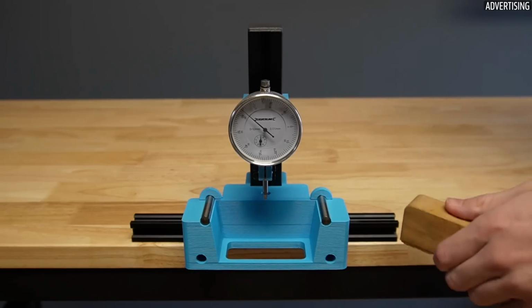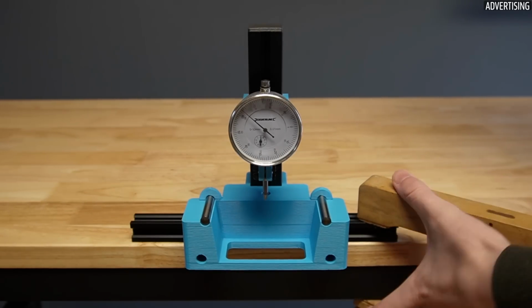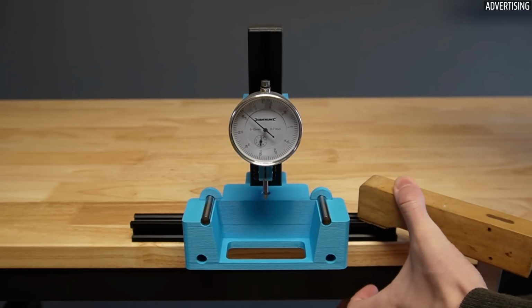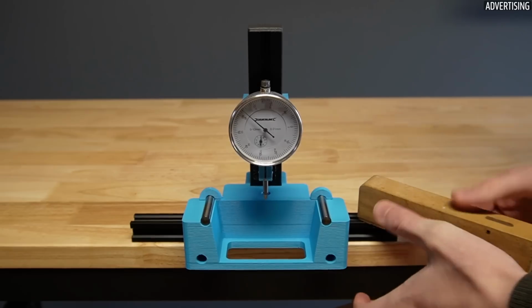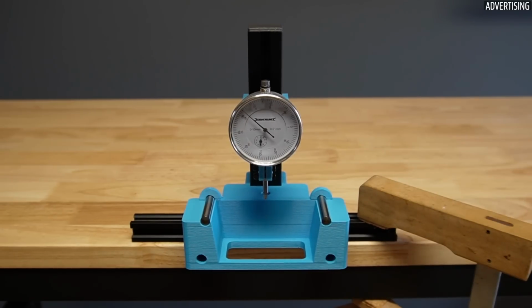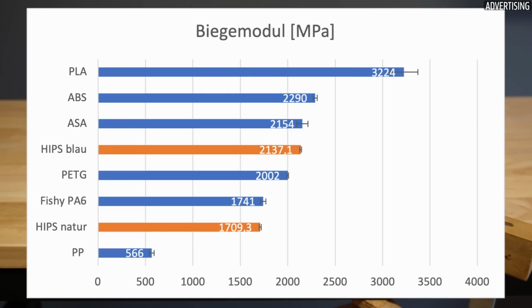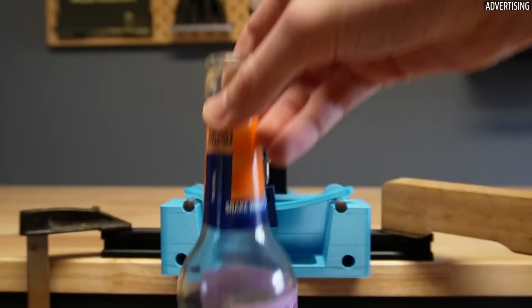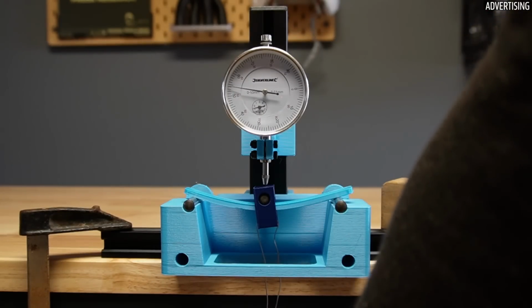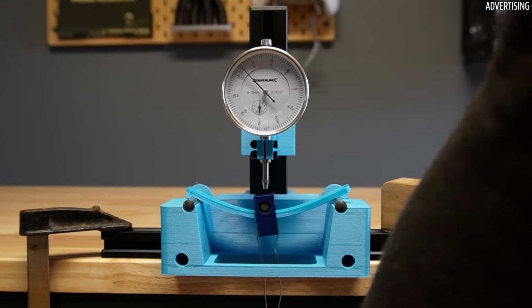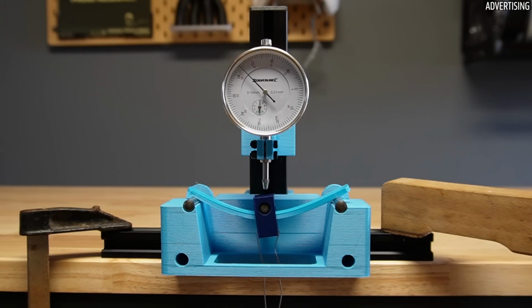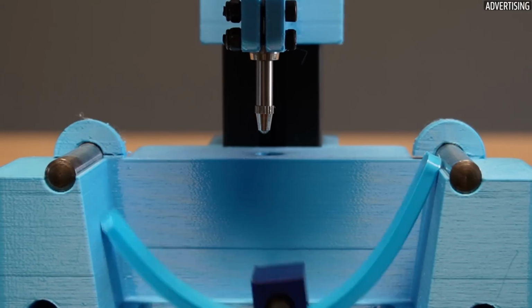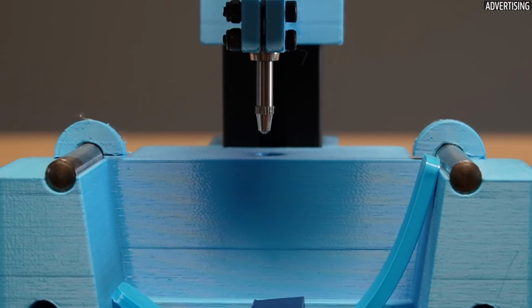With my 3-point bending test, the bending modulus can be calculated as a measure of stiffness. Normal PLA has a bending modulus of around 3 gigapascals, which is comparatively high. The high resilience PLA, on the other hand, is so flexible that it slides straight out of the measuring range of my dial indicator. I would therefore estimate the bending modulus to be below 400 megapascals.